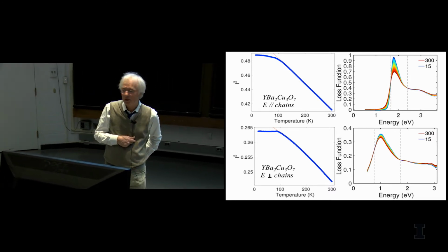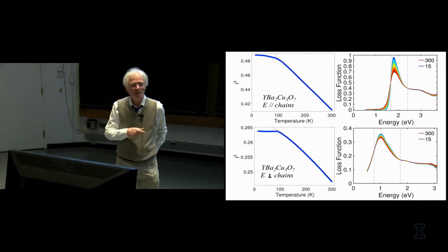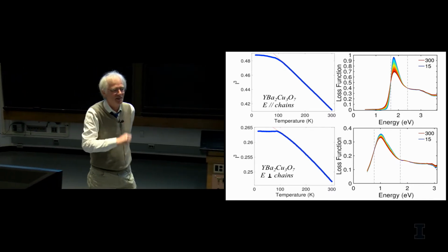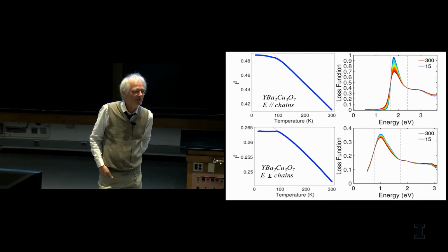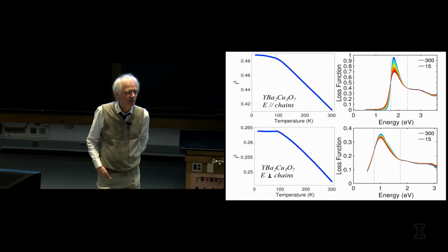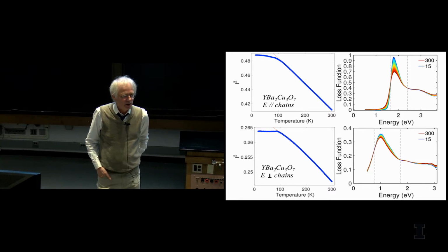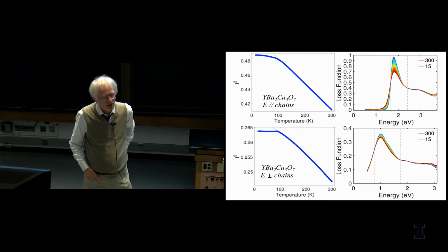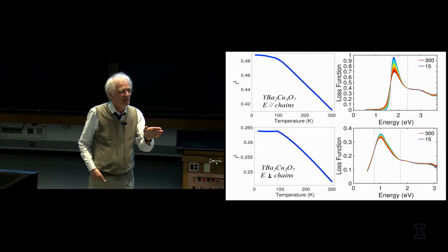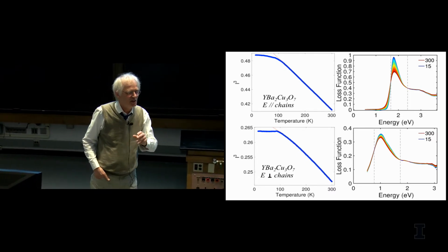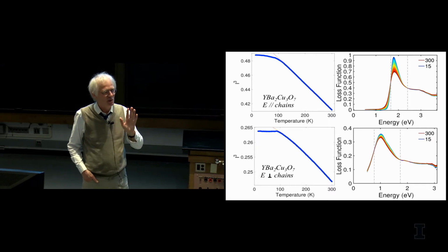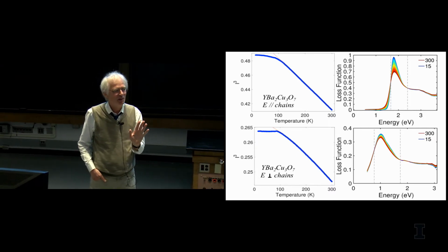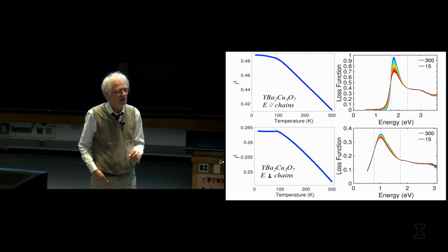So what about the C-axis? Tony had also a C-axis question. What about the C-axis response? Because this is Q equals 0, but there's still spectral weight. Yeah. Okay, read our long PRX. It is in appendix F and G, I think. If you go through all the moves, you calculate how much it could contribute, it's negligible. And that's because the plasma frequency along the C direction is so small.